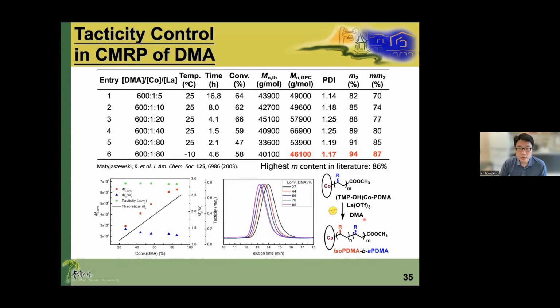So after optimization, we use the cobalt porphyrin complexes associated with the Lewis acid, lanthanide Lewis acid, and we can approach the controlled radical polymerization of DMA with the tacticity control approaching 94%. And previously, the highest value was published by my postdoc advisor, Professor Matyjaszewski, as 86%. So we obtained a higher value. But what's the specialty of getting a higher value?